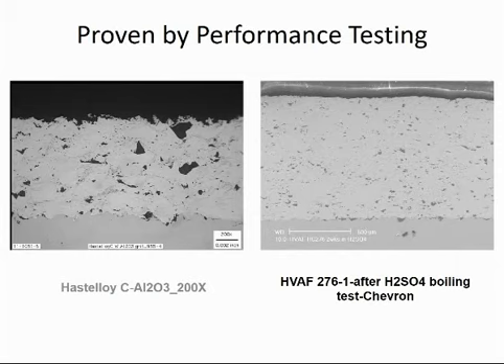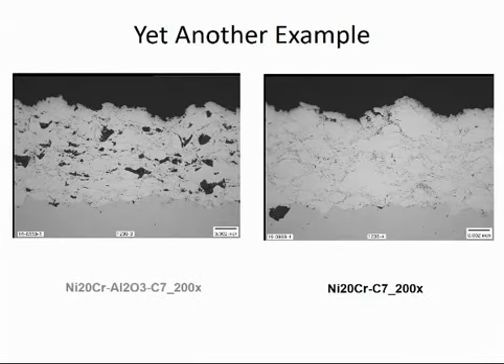And this is a really good one. This is the coating that we sprayed in testing for those vessels we sprayed for Chevron. Here's the coating in its unaffected state as sprayed with the aluminum oxide, and here it is after it's been subjected to boiling sulfuric acid. I forget how long the test went, but it was a while. Oh yeah, right here, 2 weeks. 2 weeks, and nothing happened to the coating. It looks just as good as the day it was prepared.